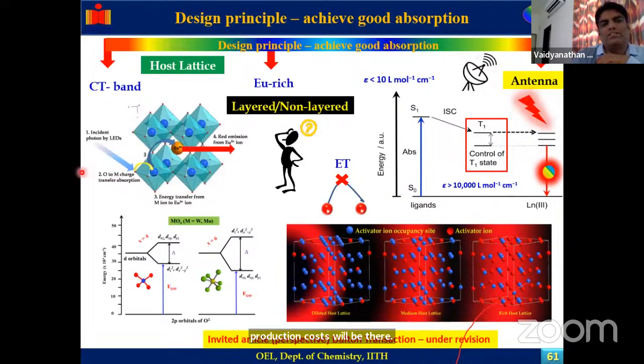So we have the incident photon absorbed by the oxygen-metal charge transfer, transferred to the europium 3+ ion, and we get an emission. If the host contains molybdate with 4 coordination, we get an emission with less absorption, whereas if you have a 6 coordination, it can absorb a little more photons. In addition, the europium-rich center: suppose I increase the europium number in the lattice, then instead of coming to the ground state, the europium 3+ emission migrates from one europium to another europium, like this. But in the case of a layered structure, well-separated europium ions are present, and hence we can get the emission without concentration quenching.